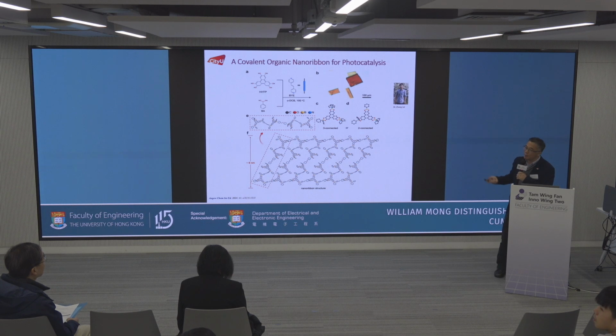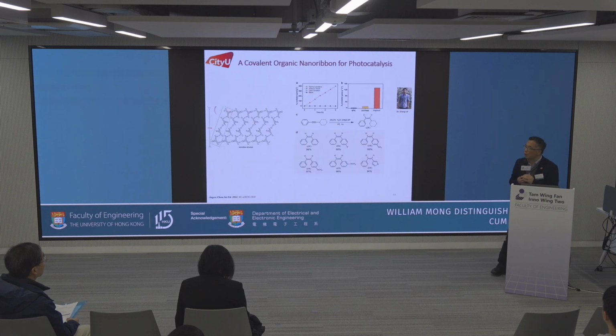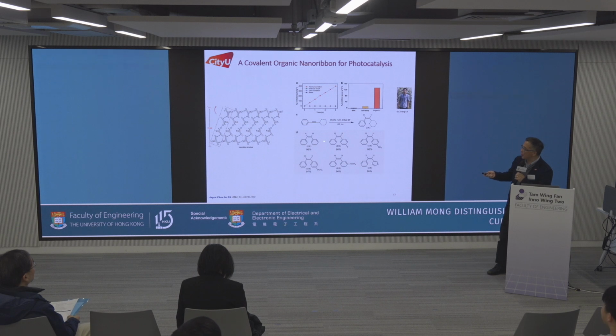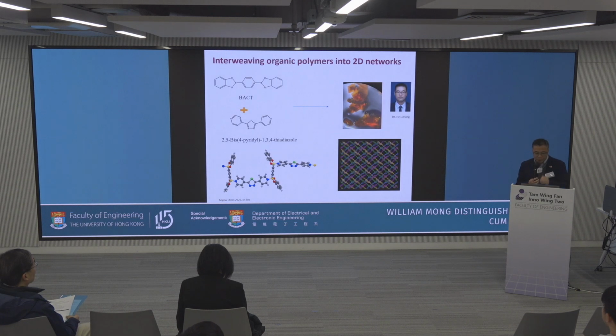Since we have this material, what application is there for this material? We found that boron unit is a very good catalytic unit, and in the dark, we cannot see any hydrogen evolution. However, when shined with light, you can see the hydrogen evolution. Okay. And then we use in situ hydrogen for addition to the triple bond, and you can see they always make the cis addition, and the yield is very good. Whether the benzene has an electron-donating or electron-withdrawing group, the yield is more than 90% and higher. And keep going.